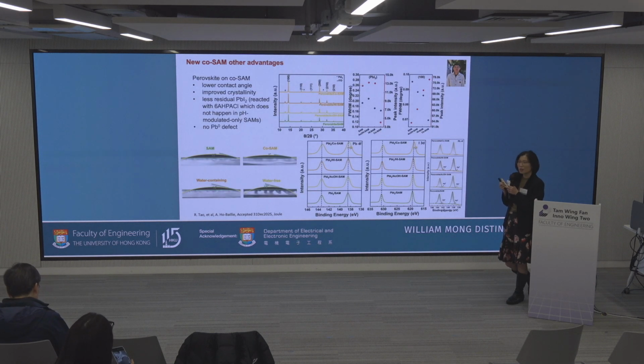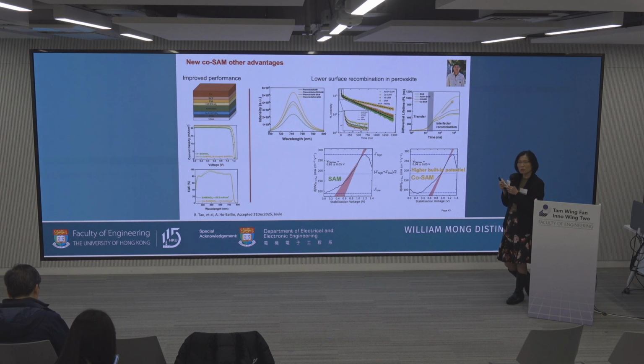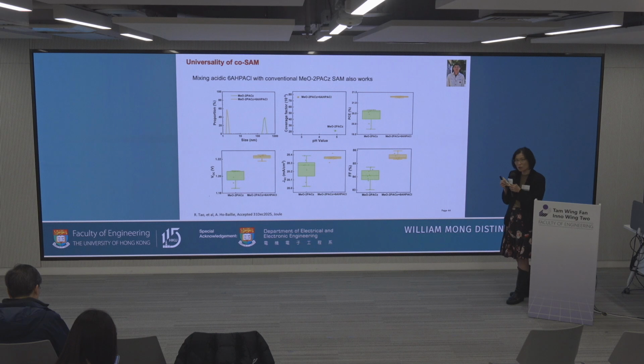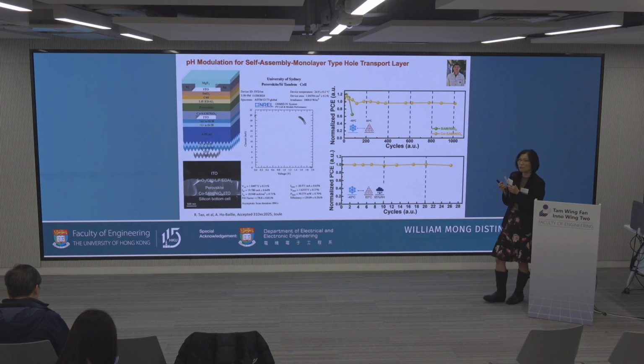So the one I showed that Guoliang produced was we were able to get the cells to pass the IEC 61215 thermal cycling test, which is 200 cycles. But in this case, we're able to get the cells to go through 1, 2, 3, 4, 5 times what the IEC requires, which is 1,000 thermal cycles. Also able to get the cell to pass another IEC test, which is the damp heat. So it's got the thermal cycling as well as the humidity.